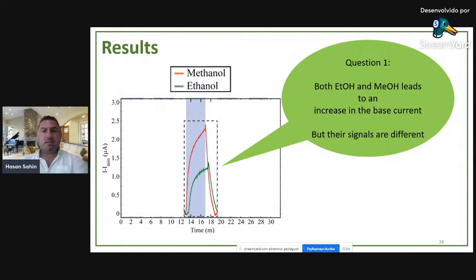And results. Let's look at our results. First of all, here we have a base current. I'm plotting here. I set it to 0. Base current is 0, and from the 13th minute, we are injecting ethanol and methanol inside the tube. Since I'm injecting extra ethanol and methanol, my base current goes up. As you see here, there is an increase in the current. It seems that both ethanol and methanol are increasing the base current. Because of their presence, current becomes larger.